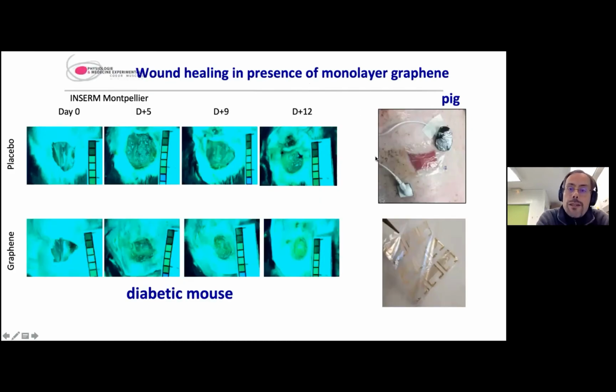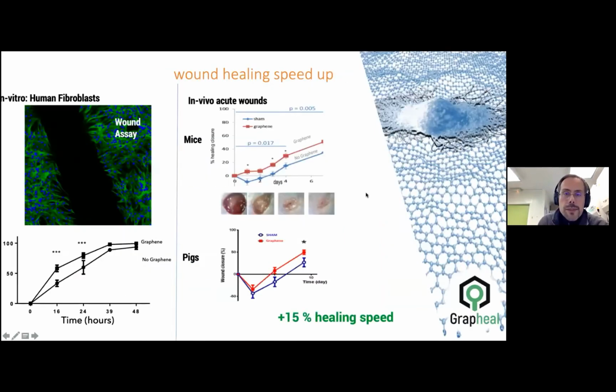And then we went to in vivo, and in that case, we use a diabetic mouse, which has a delayed wound healing. And indeed, after 12 days, you have a smaller wound when you have this polymer coated with monolayer graphene compared to the control one with the same polymer without graphene. And we did that also with pig model, which has a skin extremely close to the human skin. So this speeds up, it goes in the very few days here.